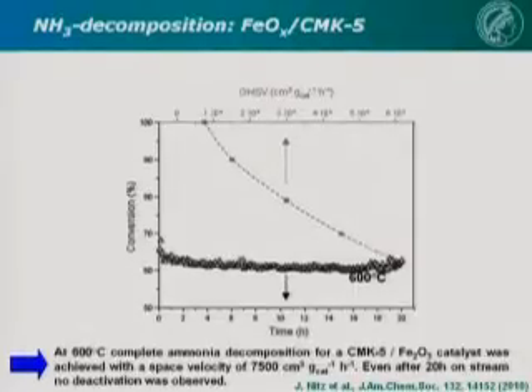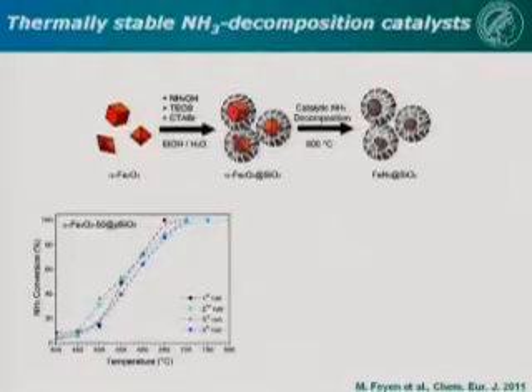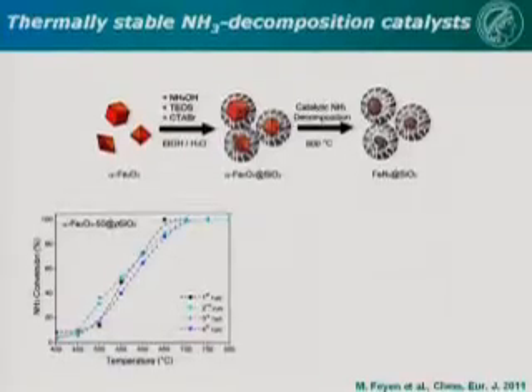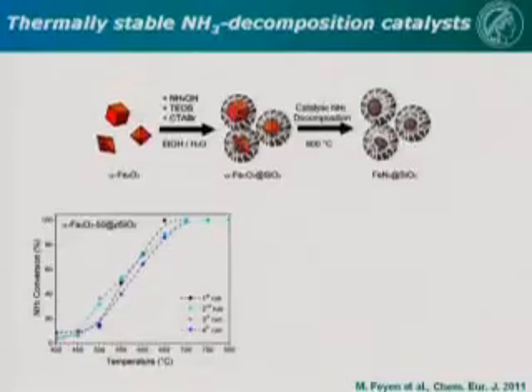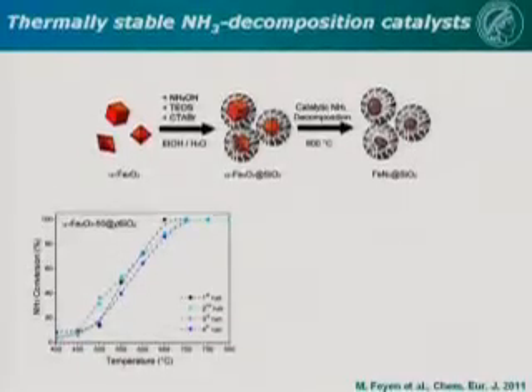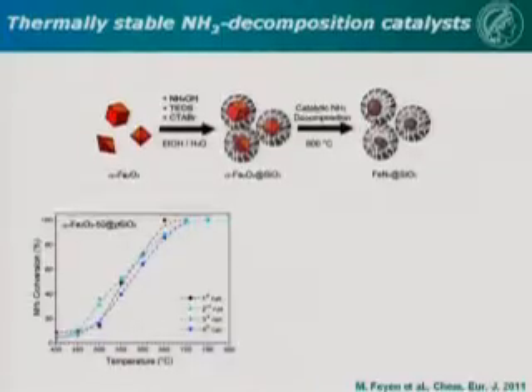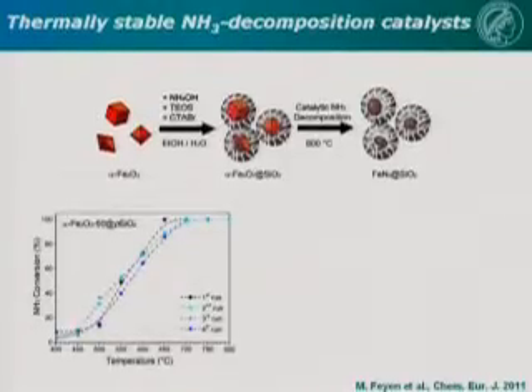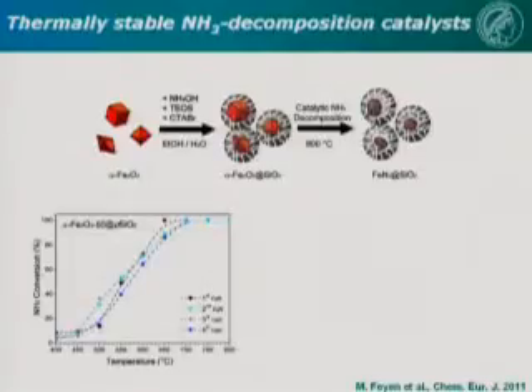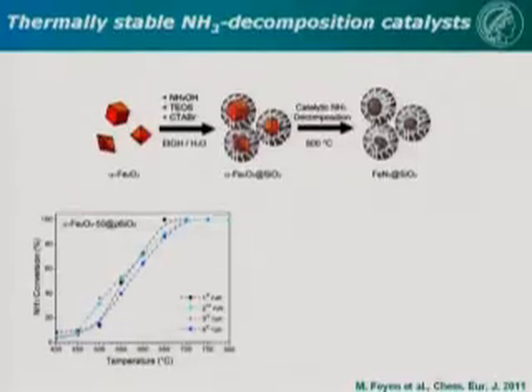Later on, we found a simpler way to produce a stable iron-based catalyst, which is also nice, especially because we prepared a nice benchmark system. It uses a similar concept, encapsulation of iron particles in a porous shell, but it works in a different manner. Here we start with iron oxide particles. We start with alpha iron oxide, but you can also use the gamma depending on how you make the nanoparticles. Sizes approximately 30, 40, 50 nanometers. And then we coat the iron oxide nanoparticles with a porous silica shell, and we create porosity by adding a surfactant again, which we burn out afterwards, and that creates then the pores in the silica shell.